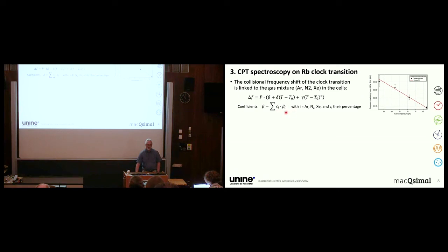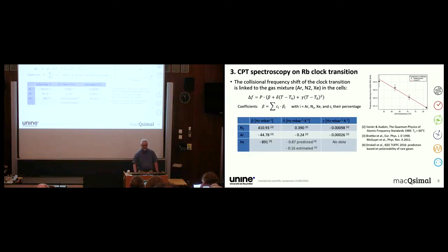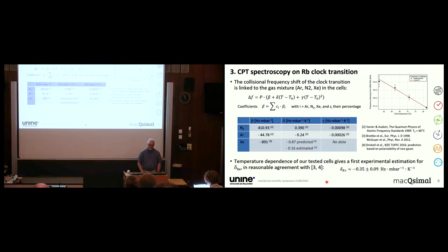And each of these coefficients can be composed as a weighted average of the pure gas coefficients if you're looking at a mixture. Now, these coefficients are quite well known for nitrogen and argon, as you can see here. But for xenon, they are much less commonly measured, and actually there's only the absolute pressure shift, which is reasonably well known. And there are diverging predictions and estimations for the temperature shift, the delta, and there's absolutely no data on the quadratic shift here. But by fitting with the available data and this second-order temperature model, we can extract from our cells a value for the delta coefficient for the xenon, which is around minus 0.35 Hertz per millibar Kelvin. So this is in reasonable agreement with the previous estimations and predictions that are available in the literature. So from these cells, in addition to looking at gyroscopes, we could also extract some basic physical parameters.